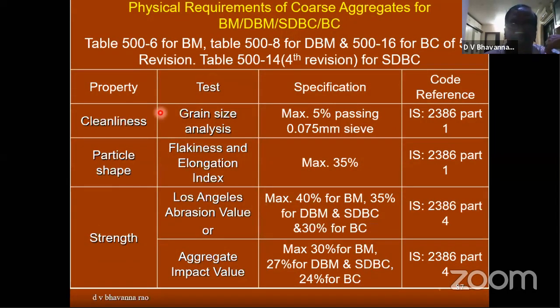These are the tests for bituminous aggregates: grain size analysis. Flakiness and elongation shall not be more than 35%. Aggregate impact value: maximum 30% for BM, 27% for DBM, 20% for BDM and SDBC, and 24% for BC. If we adopt stone matrix asphalt, it shall be less than 18%.